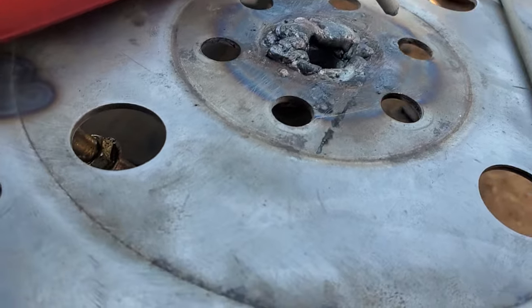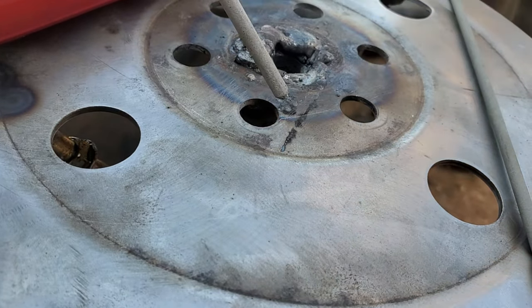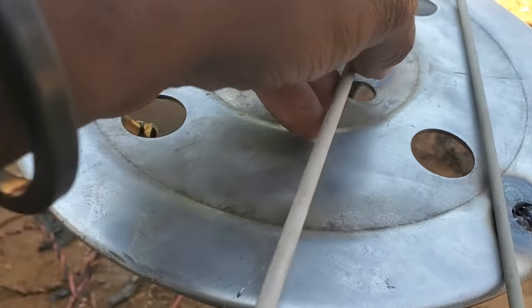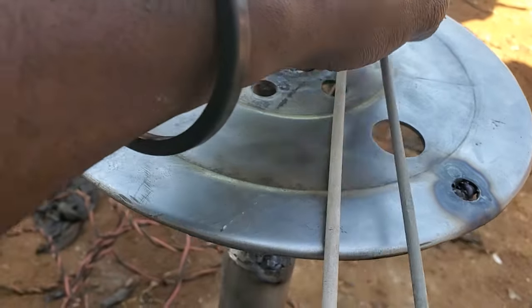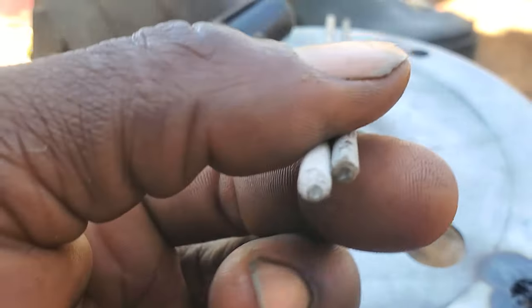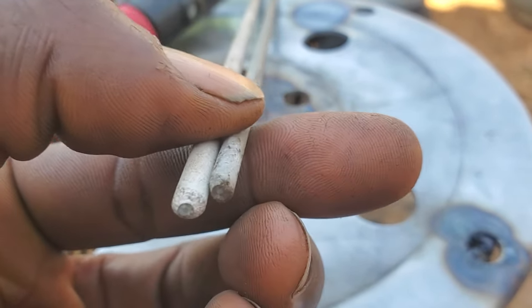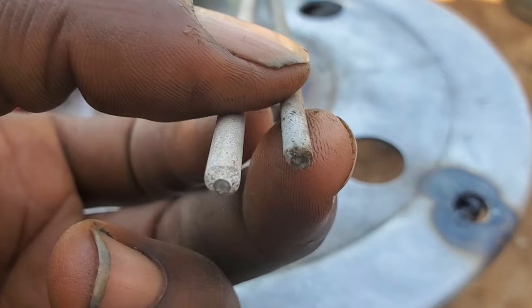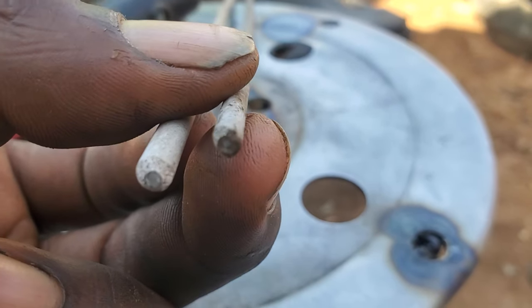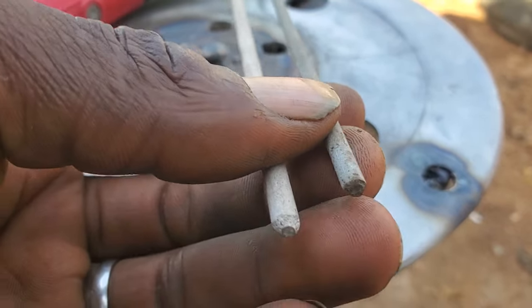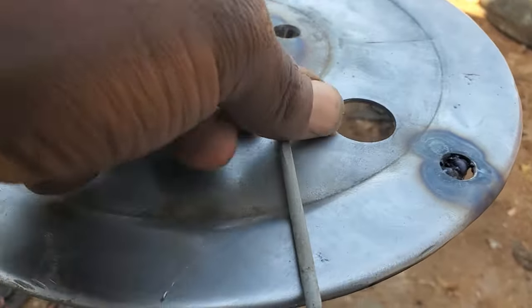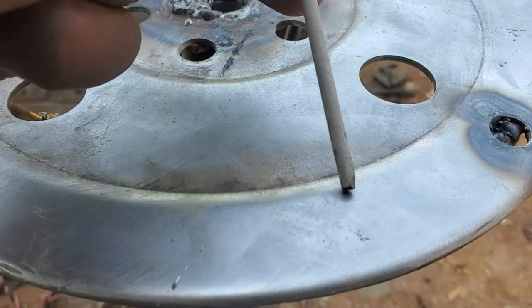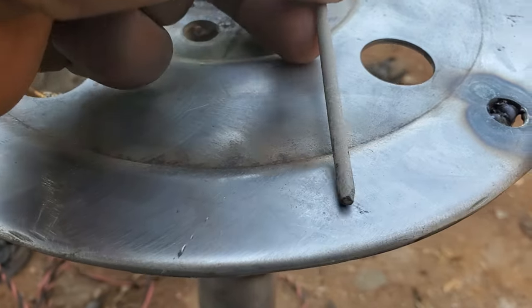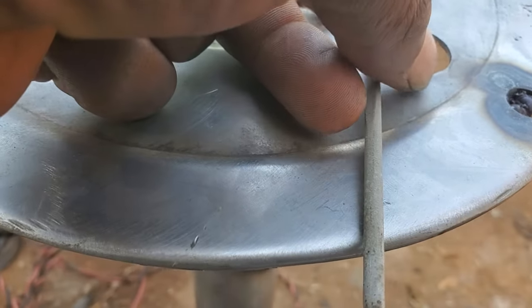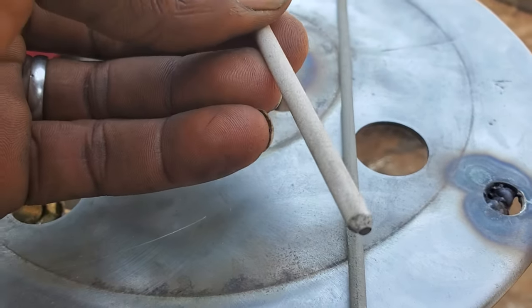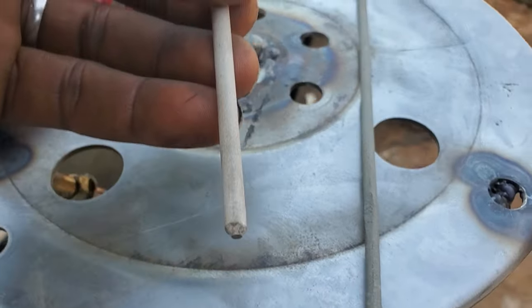Now, lastly, if I haven't gotten to 10 already, let me state this clear. If you look at this very electrode here, that's gonna be 10, which is quality material. If you look at this very welding rod, the one on my right, which is this guy here, has more thick metal inside while having the flux on the outside. However, when I'm welding using this very 6013, there is more carbon formation, puddles flowing everywhere, blistering all over the place, rather than the real metal which is supposed to be creating the joint, which is different from this one here.